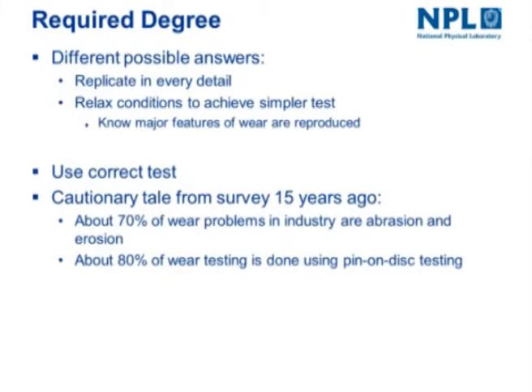The other approach, which is used by a large number of people, is that you relax the conditions to achieve a simpler test. But this really needs a lot of understanding about what's happening, so that you know which of your test conditions you can relax and which ones you can't, and you can have some surprises here. One of the checks on that is that you look at your results and check that the major features of the wear are reproduced in the laboratory in comparison to the application.